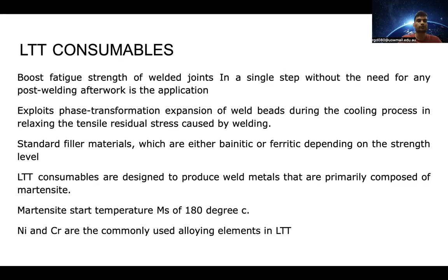Now, how do low transformation temperature consumables work? At a metallurgy level, they exploit the phase transformation of the weld beads during the cooling process, and it relaxes the tensile residual stresses caused by the weld. Standard filler materials are either bainitic or ferritic, depending upon the strength level. But LTT consumables produce a weld that is primarily composed of martensite, with a martensite start temperature of usually 180 to 200 degrees centigrade. This gives a rapid cooling, which makes the joint more robust with high fatigue strength, thereby increasing the life of the joint.